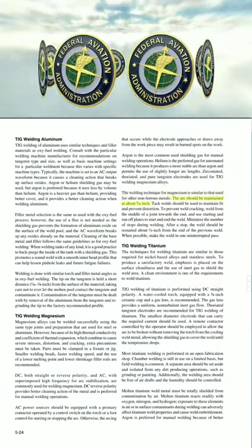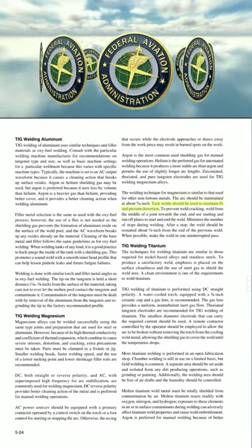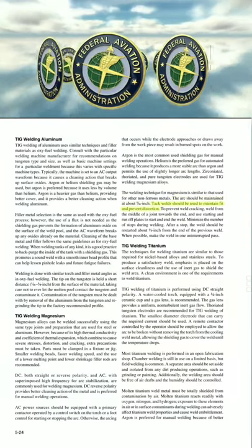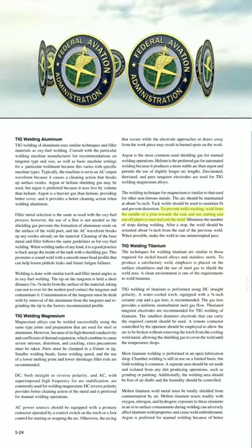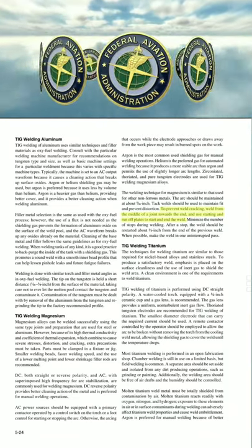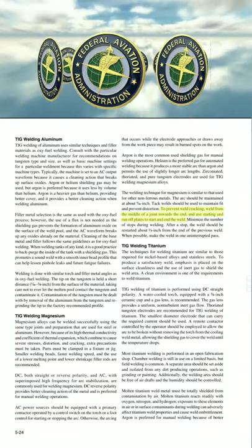The arc should be maintained at about 5/16 inch. Tack welds should be used to maintain fit and prevent distortion. To prevent weld cracking, weld from the middle of a joint towards the end, and use starting and runoff plates to start and end the weld.